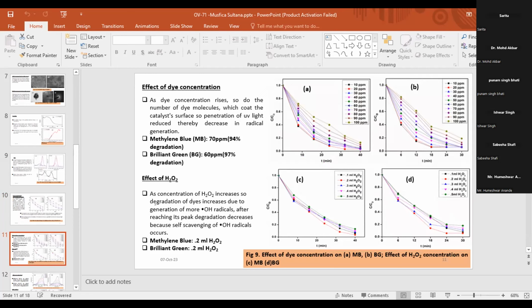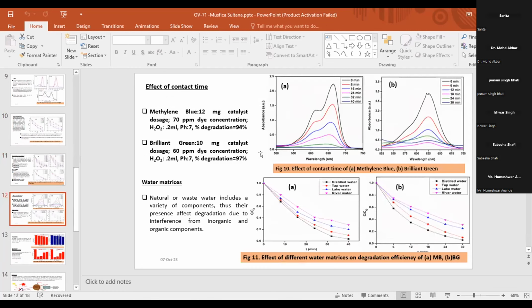And when the effect of H2O2 is seen, 0.2 ml gives high degradation efficiency. After that, the degradation efficiency decreases because of scavenging of OH radicals. And when the contact time is varied, it is seen that at 40 minutes, 94% degradation of methylene blue has taken place, and for brilliant green, 97% degradation occurred in 30 minutes.